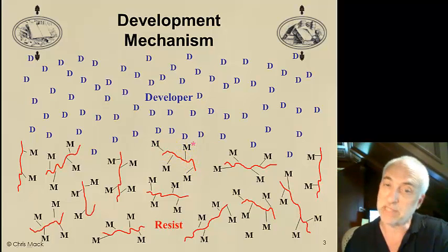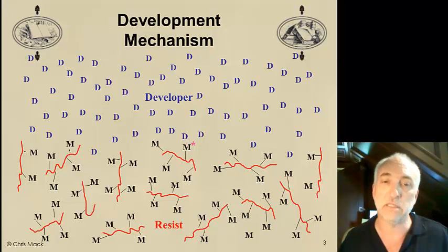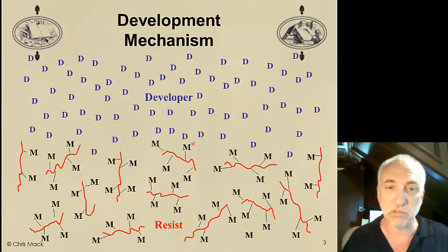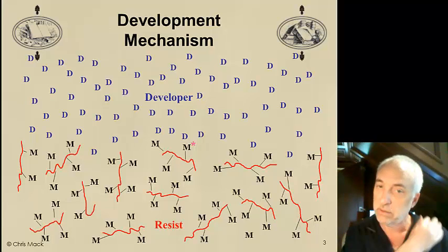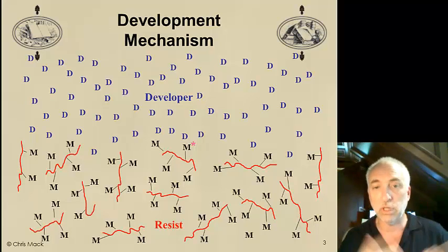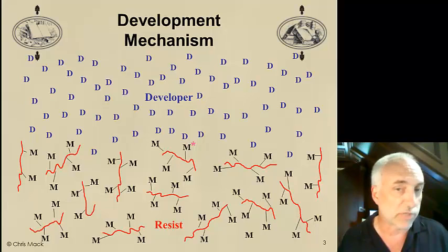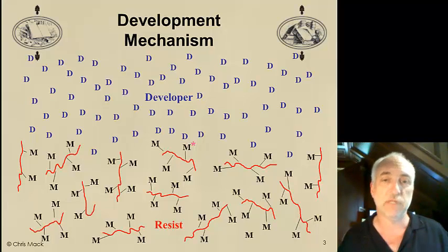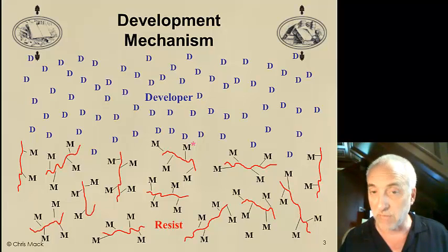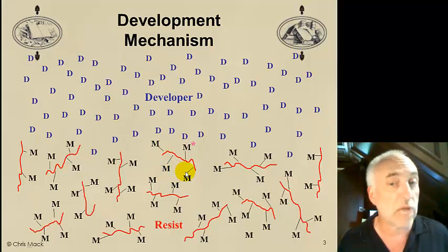Unfortunately, that polymer has 3 other protected sites that do not like that developer at all and inhibit the dissolution of the resin. So what happens? Well, I'm sorry, that one lonely deprotected site is not enough to get the polymer to go into solution. The 3 protected sites win out, they hold it back, and we do not get dissolution.